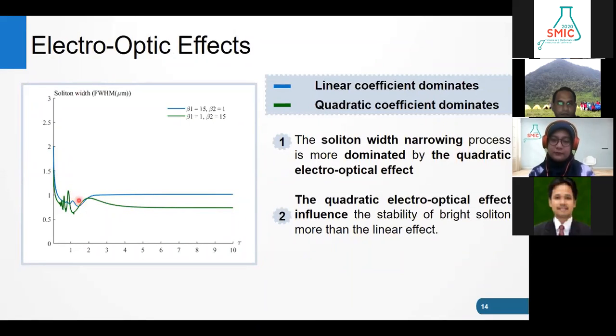The blue line presents the case where the linear electro-optical effect coefficient dominates, and the other line presents the case where the quadratic electro-optical effect coefficient dominates. From the curve, the soliton is more dominated by the quadratic electro-optical effect, and we know the quadratic effect influences the stability of the bright soliton more than the linear effect.